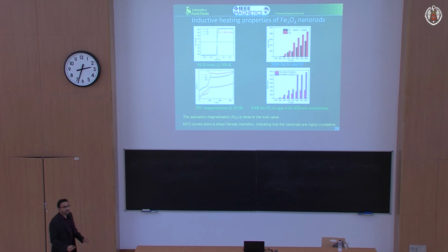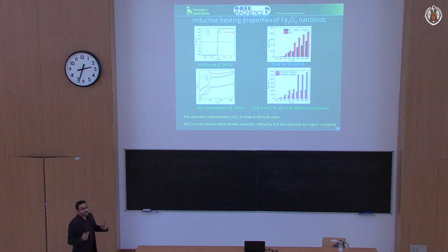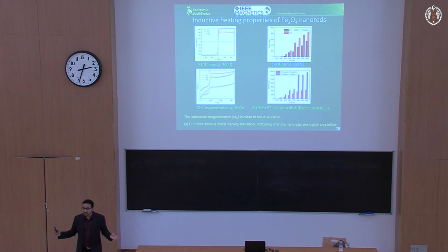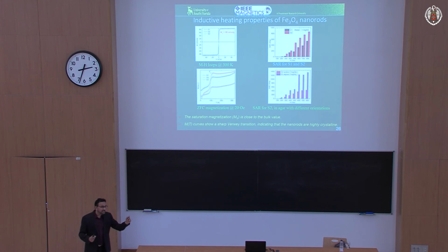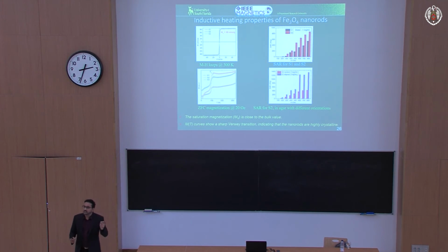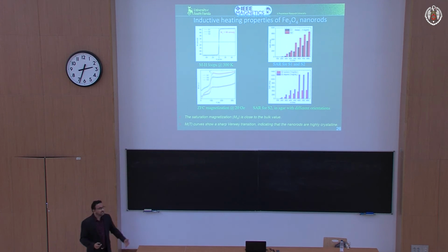We had SAR values, and some of these SAR values are very, very impressive. One of the highest SARs reported in iron oxide, magnetite, the basic biocompatible iron oxide material. So we can go way beyond spherical particles and increase the SAR. We can also do some alignment, and we do this by magnetic alignment, typically in an agarose gel. We use that to align the particles, and we can improve the SAR even better.